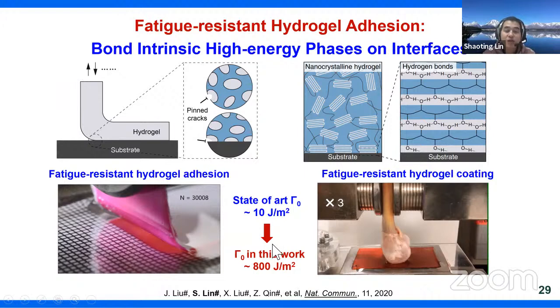We measured it from 10 to 800. This is our measured result, and we also used X-ray scattering to characterize the gradient structure that develops from the substrate and with distance away from the substrate. We also found that in many biological systems, for example soft tissue, muscle, tendon and connective tissue, there is a similar ordered structure from the bone to the soft tissue. Interestingly, this crystal structure is helpful for the adhesion energy at the interface. This is my understanding of this high interfacial process.